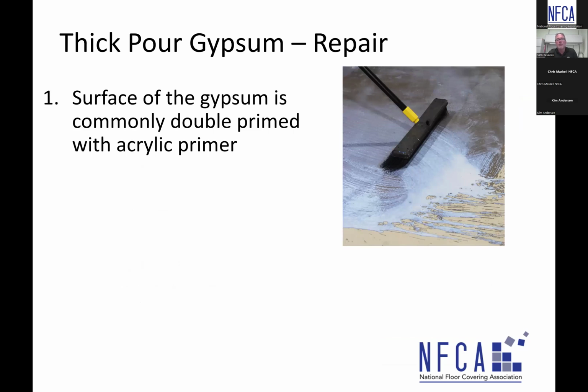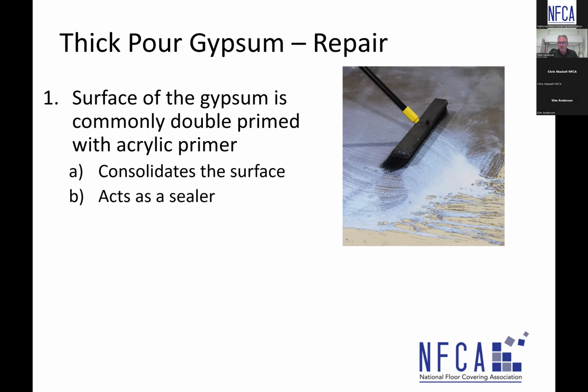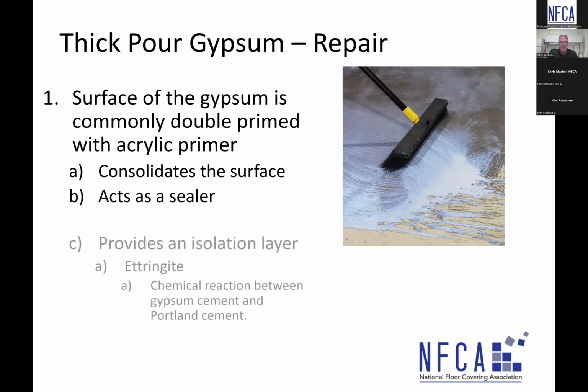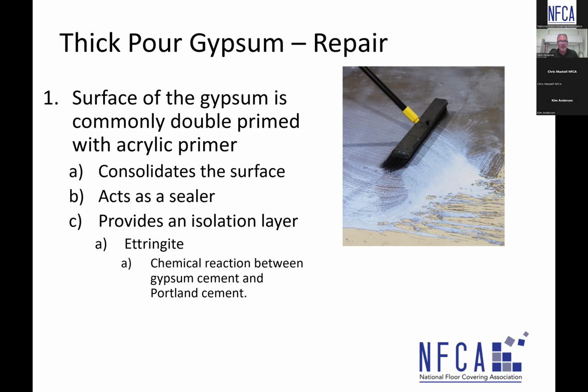So when we're installing patching or leveling materials over gypsum, double priming, very common with an acrylic primer. This helps consolidate the surface. It certainly acts as a sealer so that the gypsum isn't sucking water out of the patch or the leveling material. But without getting too terribly technical, it creates an isolation layer if a Portland cement product is used on top.